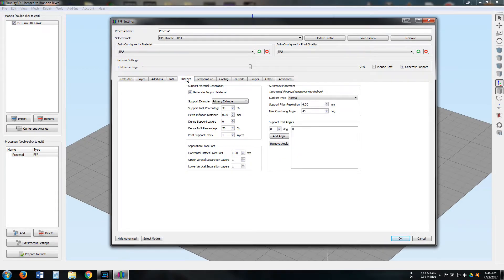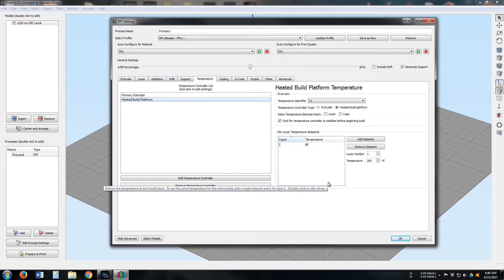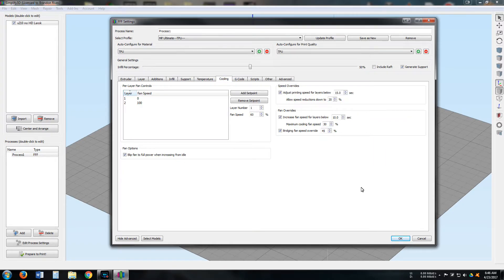The Support tab — once again, the majority of these settings can be adjusted. The Temperature tab is where some people will say lower or higher temperatures will work; this is what works for me: build plate at 60°C and primary extruder at 220°C. For Cooling, I use zero percent at layer one and one hundred percent at layer two.